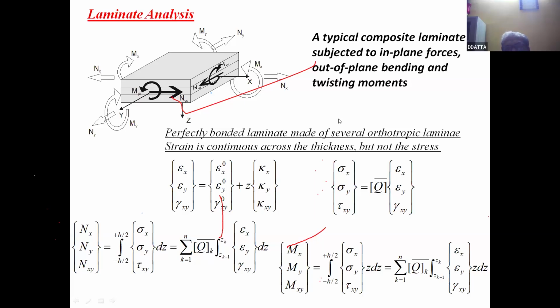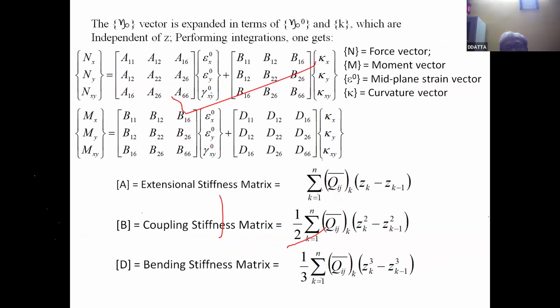So this is what classical lamination theory is about. The load and moments can be expressed in terms of stiffness and the strain components. And finally, the load is expressed as this stiffness matrix A times mid-plane strain plus B times curvature. So what is the beauty of this equation is that it tells you clearly that even if you apply in-plane forces on a laminate, there will be mid-plane strain, that is fine, but also there will be curvature.